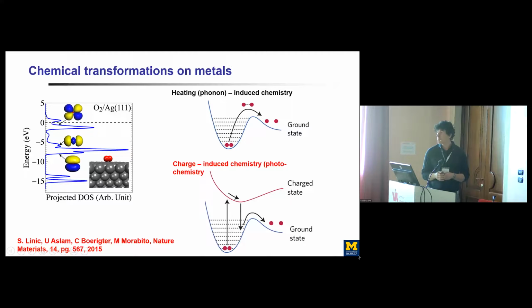Same process can take place in an alternative mechanism where you have a way of somehow taking an electron out of this nanoparticle and depositing it selectively into this oxygen-oxygen anti-bonding orbital. In this process, you go to this charged state. You're creating a transient negative ion, but basically doing the same thing. You're putting an electron in this anti-bonding state, and now you introduce forces on these oxygen atoms, and these oxygen atoms are now starting to move away from each other, and you're exchanging that electronic energy for vibrational energy, and you can induce chemical transformation that way.